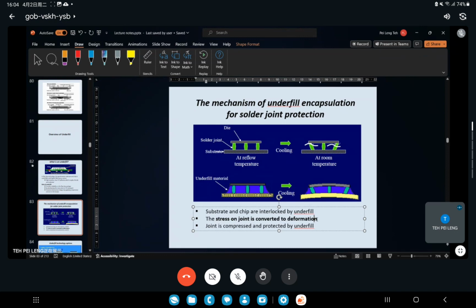Because of the CTE mismatch between these materials. Especially the die, you have 2 to 3 ppm per degree Celsius, the substrate 80 to 100 ppm per degree Celsius, and this solder joint is around 20 to 40. So different shrinkage and different expansion rate, so you will generate thermal stress. If without underfill, the stress will all go to your solder joint, will all go to your bumps.